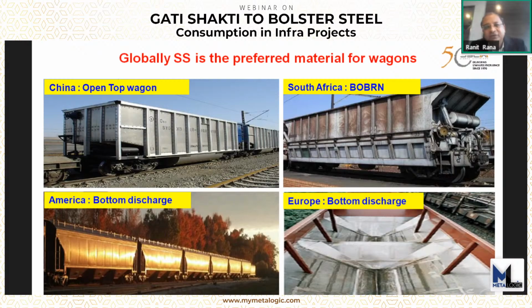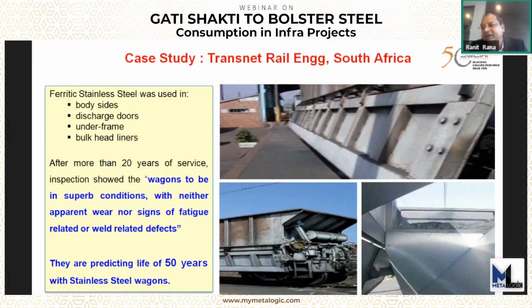Now, if you look at it globally, stainless steel is the preferred material for wagon manufacturing across the world. And I'll just share with you one case study from South Africa, where these bottom discharge wagons have been completely made out of stainless steel, the shell and the underframe, and this is the condition of the wagons even after 20 years of service. That means there is absolutely no corrosion, there is absolutely no weld-related fatigue or cracks. And what they are predicting in South Africa is that a stainless steel wagon could last them for 50 years.